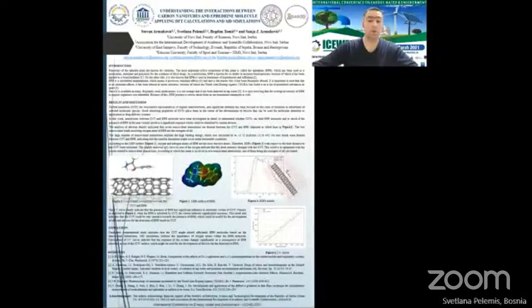The 2 non-covalent bonds involving the oxygen atom of ephedrine are strongest of all. The large number of non-covalent interactions explains the high binding energy, which was calculated to be minus 11.52 kilocalories per mole. Regarding the radial distribution functions, the slightly narrower GFR curve in case of the oxygen indicates that this atom interacts stronger with the carbon nanotube than nitrogen.